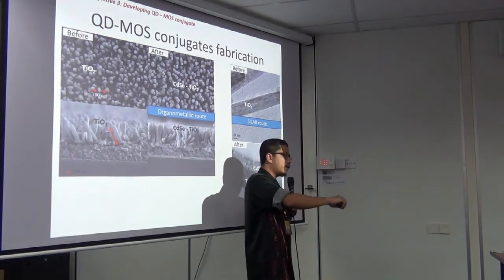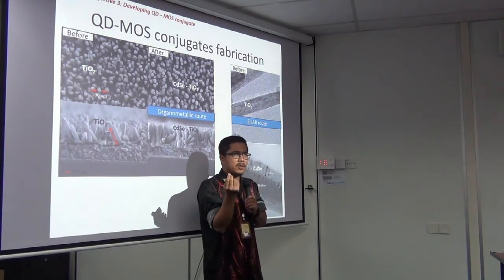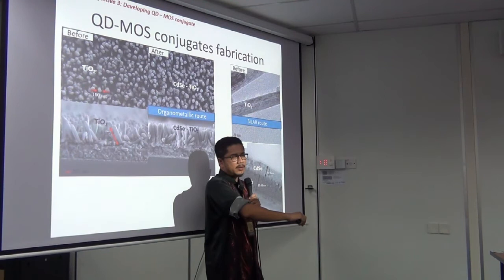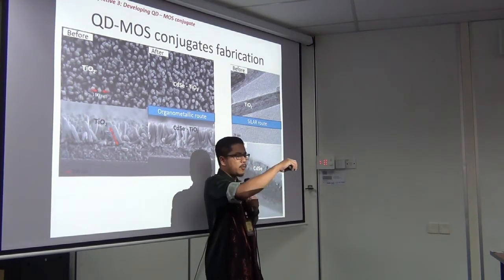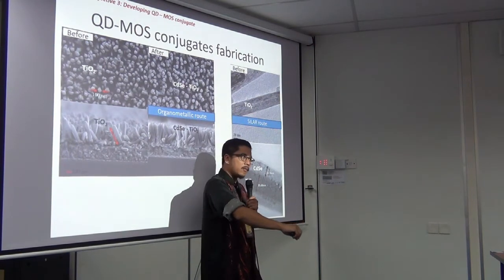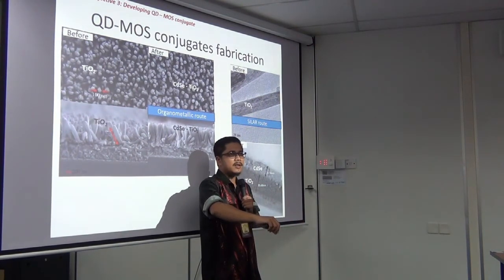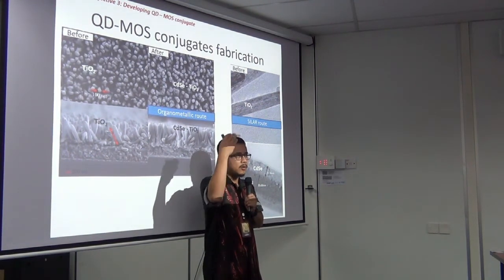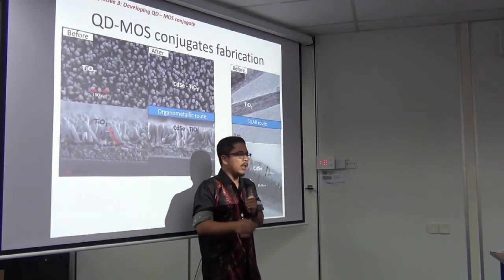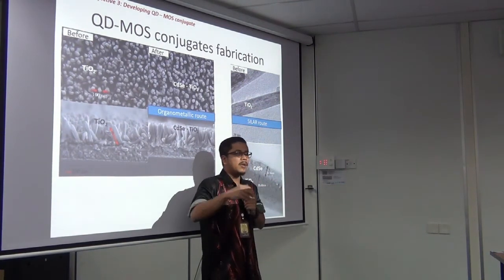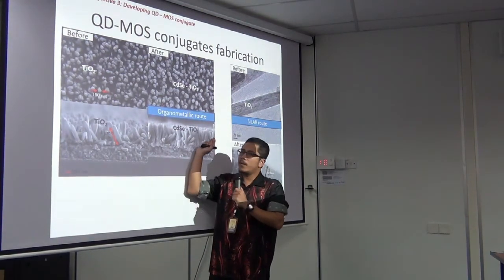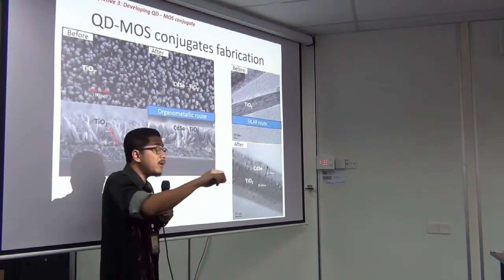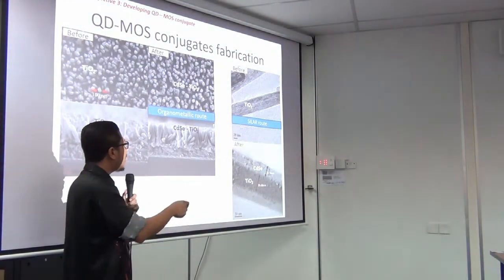So first we dip our TiO2-coated glass into the cadmium salt precursor solution. Then we dip for a few minutes in ethanol. Then we dip into the third beaker, which contains the selenium salt, and we dip into the ethanol. Then we get CdSe produced onto the surface of our MOS. We repeat that cycle a few times. Then finally we get full absorption of CdSe quantum dots onto our MOS. Just a dipping technique, a simple technique, but the name is lengthy.